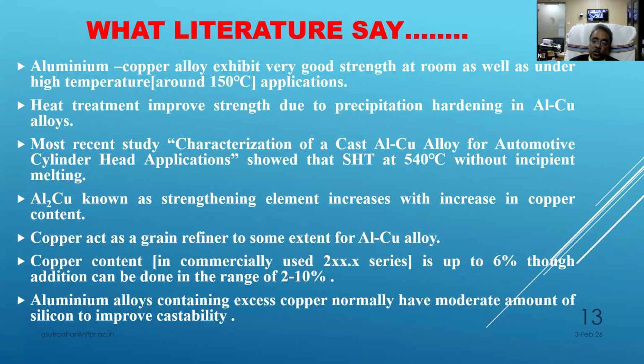So here literature says the copper in aluminum could be 2 to 10%, but the study gives you more detail: what is the percentage at which you can get the most suitable mechanical and metallurgical properties as well as castability. Material property is very good, but if it is not castable, that means no use of that. So we have found in our study what percentage of copper in aluminum will be best in castability as well as desired, or you can say optimum, mechanical and metallurgical properties.